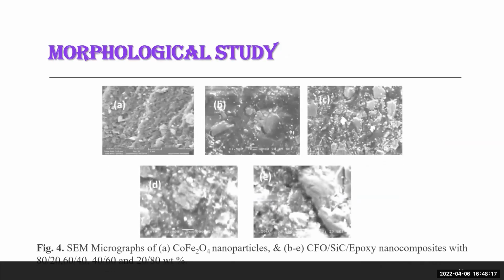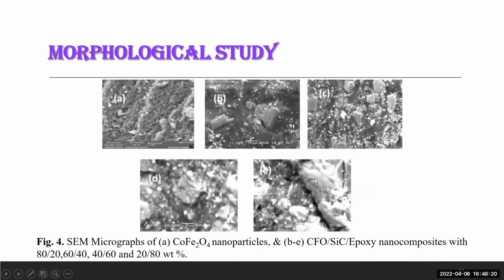The microstructure and surface morphology of the cobalt ferrite silicon carbide epoxy nanocomposites was studied using the SEM technique. Figures A to E show the SEM micrographs of the samples. A shows the SEM micrograph of cobalt ferrite in the form of powder, and B to E show the cobalt ferrite silicon carbide nanocomposites of different weight percent in the form of pellets. The analysis of the SEM images shows that the nanoparticles have an almost homogeneous distribution, and some of them are in agglomerated form, which confirms the pore-free material with uniform distribution.